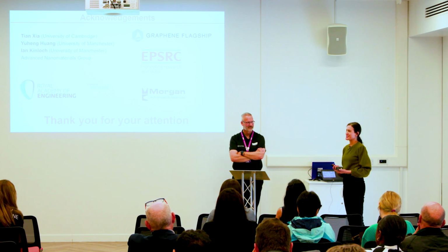Very interesting questions. The first one, I guess in terms of manufacturing composites, we can use this technique. The only problem I see here is more or less the scaling up, because if you need to fill all the epoxy resin you are actually using for the whole components, for example, with graphene, that means that you are going to need a lot of graphene.